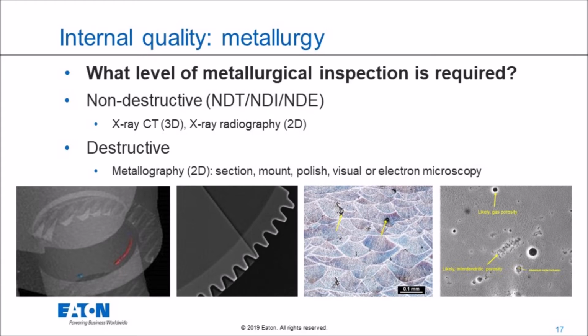In casting, you get spherical pores. They might be large, they might be horrifyingly large, if you looked at a casting, but they're spherical and they don't really create stress raisers. In metal powder bed, you can get weird, jagged pores. You can also get gas porosity, but pores like this, due to lack of fusion or keyholing, do create stress raisers, and we're not necessarily sure how that affects the fatigue life of the material, for example.